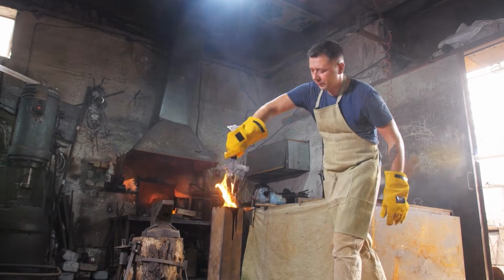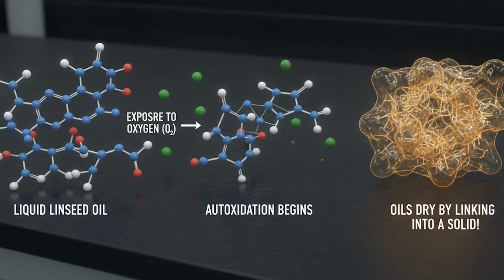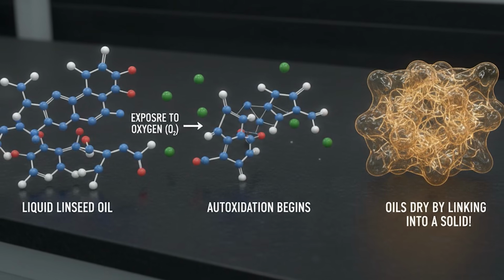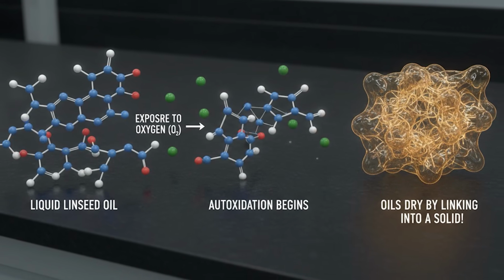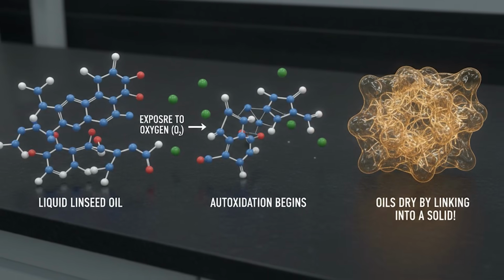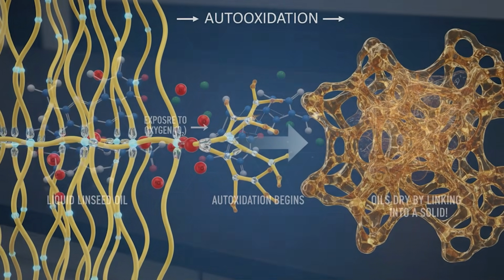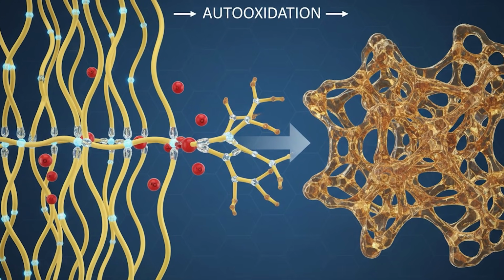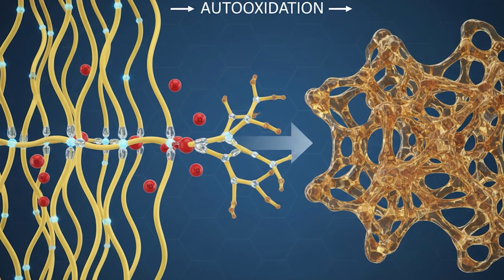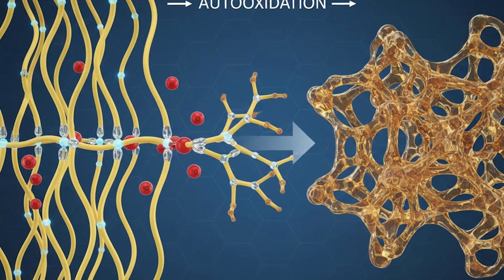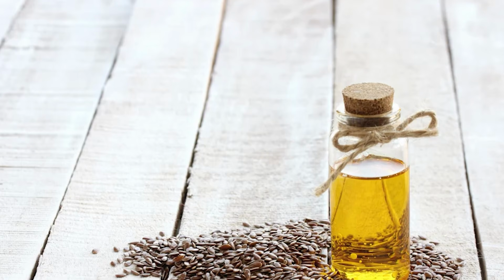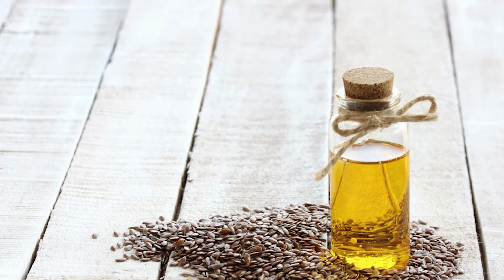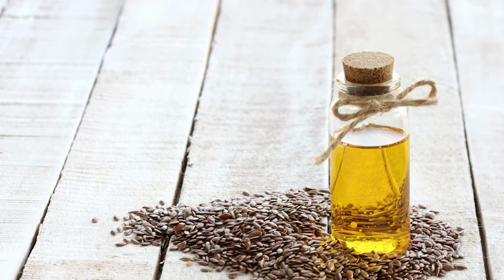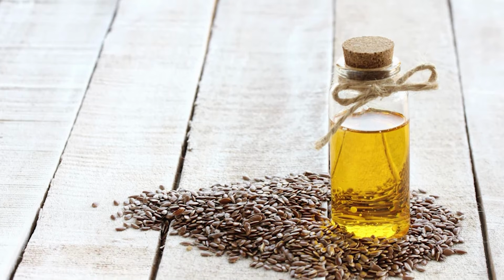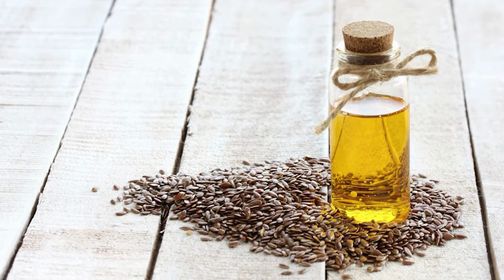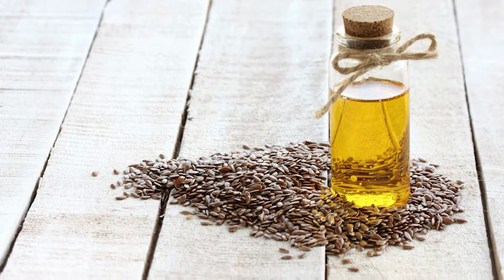Here is the science. The polyunsaturated fatty acid chains in linseed oil contain multiple double bonds between carbon atoms. When these bonds are exposed to oxygen, they break open and form cross-links with neighboring chains. This is called autoxidation. The individual oil molecules stop being independent and begin connecting into a vast three-dimensional network. The liquid oil literally transforms into a solid polymer. This is not a metaphor. Linseed oil becomes plastic, not the kind that comes from petroleum, a natural, durable, cross-linked polymer that bonds directly to whatever surface it was applied on. And when that surface is hot iron, the bond is permanent.